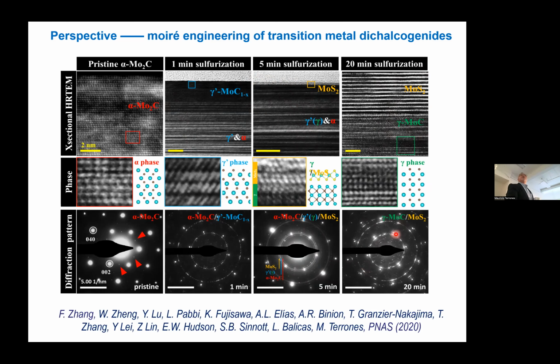And then here we just go back to three rings. But then you transform from alpha molycarbide to gamma molycarbide, which is not the gamma prime. So we have to go through gamma prime to get to gamma molycarbide. So this is what we did, and we measured the.